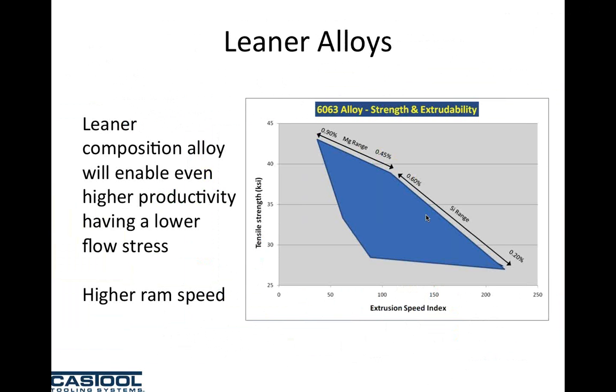When you look at any alloy, and 6063 is a good alloy to look at, the chemistry is actually quite broad. So if you go tensile strength against extrusion speed, and within this matrix here, we have different magnesium silicide recipes. And as we change the magnesium silicide, we can actually change the flow stress of the alloy. The super extruder wants to operate as far to the right as possible, depending on the tensile strength he wants. By doing this, he's leaning out the alloy and reducing the flow stress.